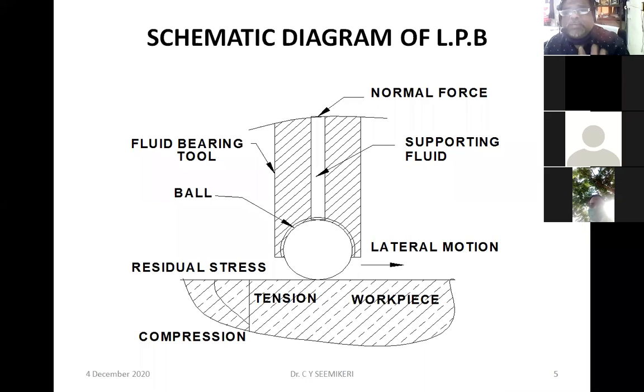So this is the basic aspect. This burnishing is done by fluid pressure, not by mechanical pressure. That's why it's called the low plasticity burnishing tool. The applied pressure is very less, 0.6 megapascal, but 1 megapascal also. So a very small pressure has been applied. The beauty, friends, is that you require a little lesser pressure on the surface. If you apply more pressure on the surface of the component, there will be destruction of the surface. More plasticity means more dangerous.